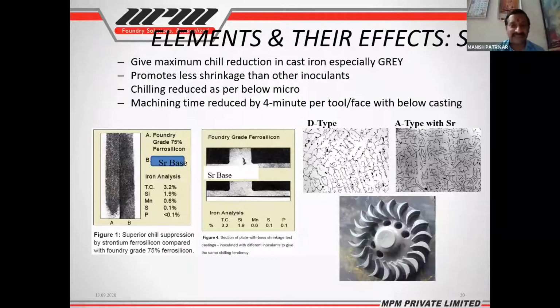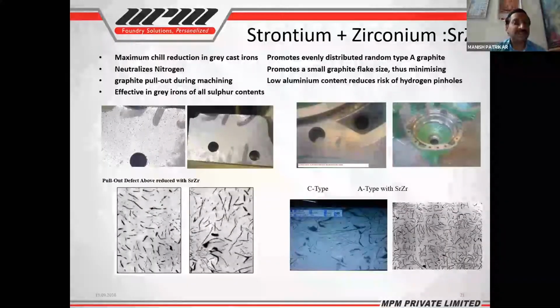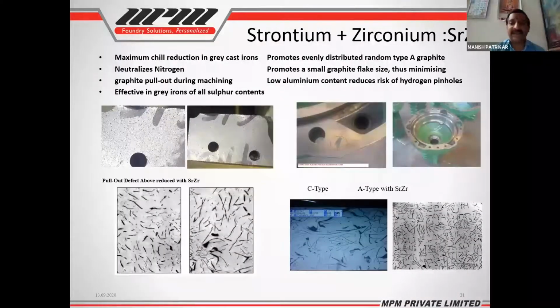So here is a casting which I have shown. We have done some study with this casting, where in the fin region over here, they were having D-type formation, and they were using barium based inoculant. But with the use of strontium based inoculant, the shrinkage tendency has reduced and the machinability has improved. So strontium plus zirconium, I'm trying to show from the case study perspective.